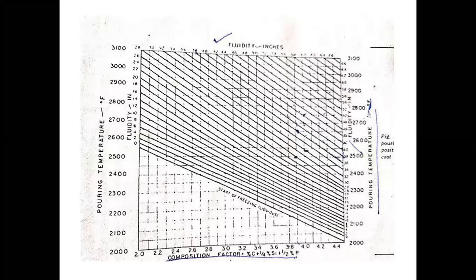That's why I suggest please pour the fluidity spiral. And for pouring temperature, what is the value that we have to consider normally? Normally, what I already told, last box. If you are pouring 10 or 12 boxes in a row, the first box will be around 1410, and the last box will be around 1370 as per the ladle condition. If the ladle is preheated, a good one, the temperature drop will be around 20 or 30 degrees.